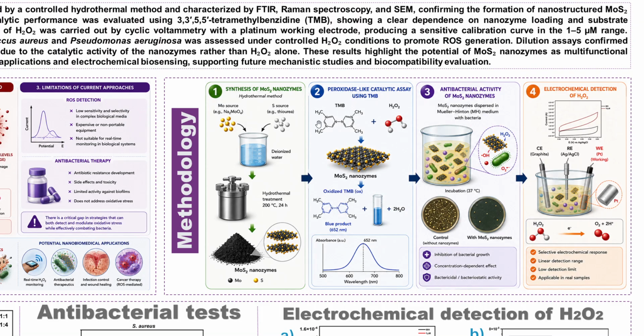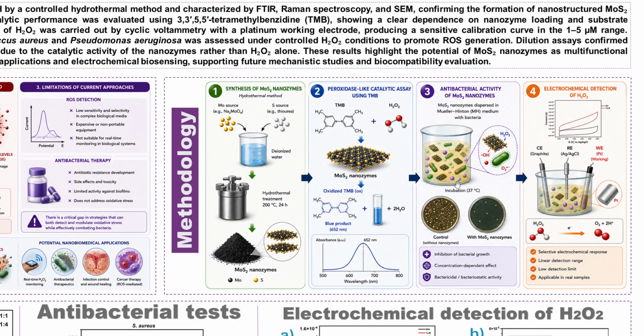Next, their peroxidase activity was evaluated using TMB. In this reaction, molybdenum disulfide catalyzed the reaction between hydrogen peroxide and TMB, producing oxidized TMB, which has a characteristic blue color and an absorption band around 652 nanometers. We also evaluated the antibacterial activity against two bacterial models, Staphylococcus aureus as a gram-positive bacterium and Pseudomonas aeruginosa as a gram-negative bacterium. Finally, hydrogen peroxide was evaluated electrochemically using a platinum working electrode, and ROS production was investigated additionally using fluorescent probes.